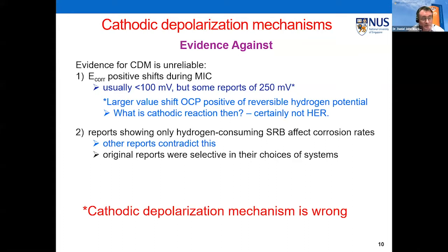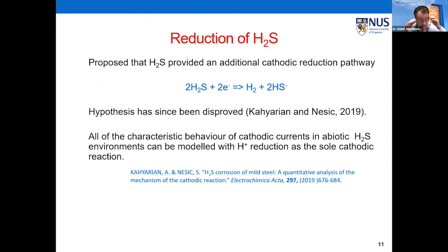And then, of course, there are problems with reports showing that only hydrogen consuming SRB affect corrosion rates, while other reports show that even if it's not a hydrogen consuming SRB, it still affects corrosion rates. So I'm fairly certain the cathodic depolarization mechanism is wrong, but what I'm less certain of is what's correct. Another idea put forward is that H2S is an alternative cathodic pathway for hydrogen evolution, involving the H2S molecule. But Nesic published a modeling study last year showing that, in abiotic systems with H2S, the cathodic currents can always be modeled simply by the standard H+ reduction. You don't need some special reaction involving hydrogen sulfide directly.